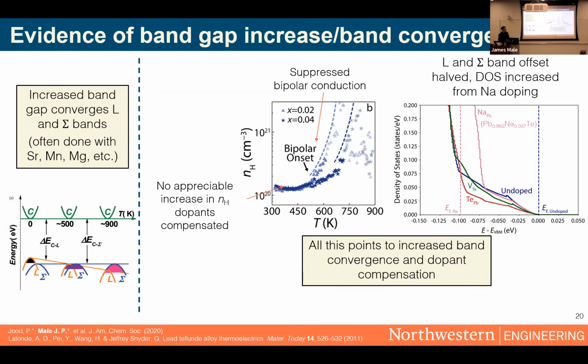We see this experimentally through varied routes, but one significant one is the Hall carrier concentration, which undergoes bipolar conduction at higher temperatures when we have more sodium, suggesting the band gap is increased. We also see that the carrier concentration is not really altered. So this means we have more sodium in the lattice, but we're not actually seeing more doping. In fact, this is most likely due to really heavy compensation by intrinsic defects.